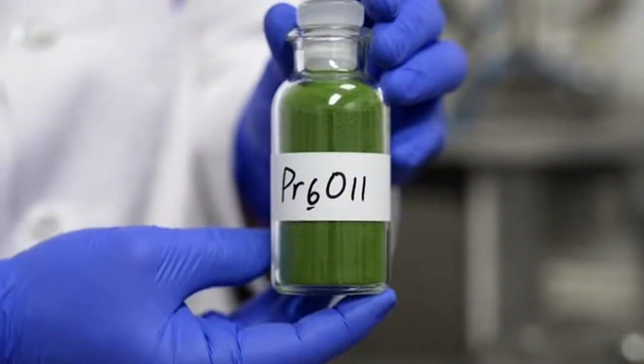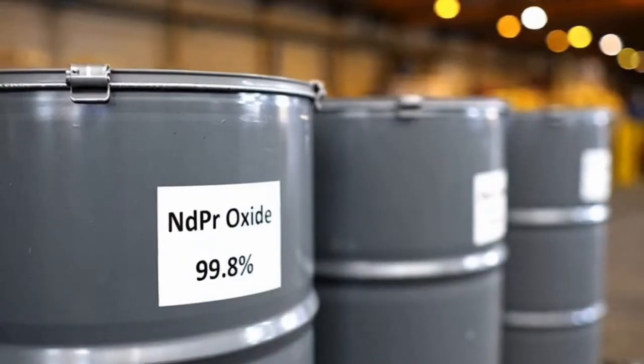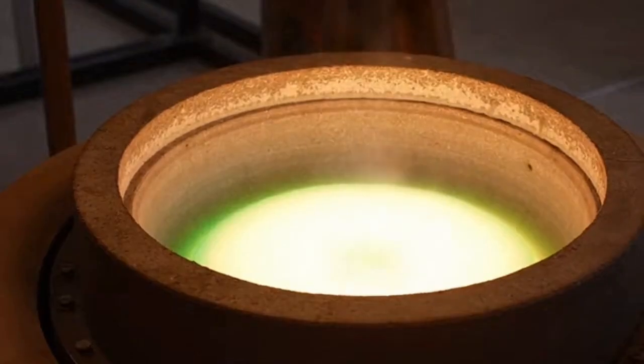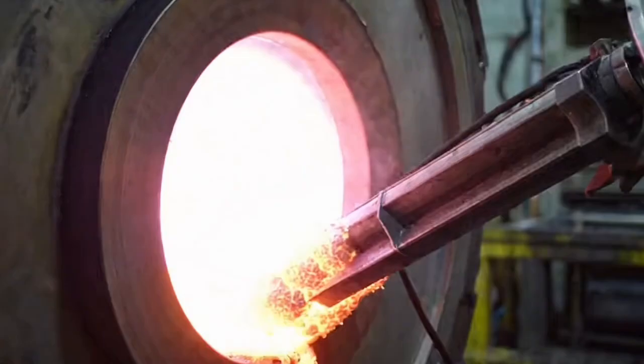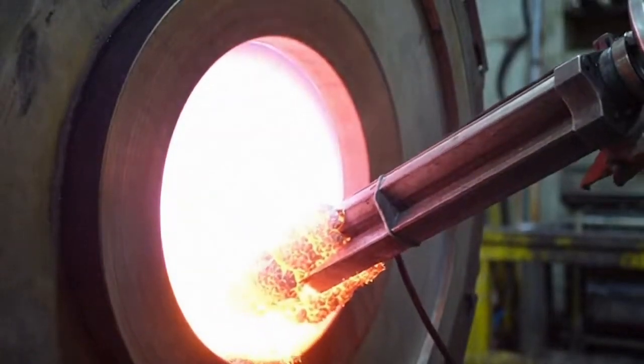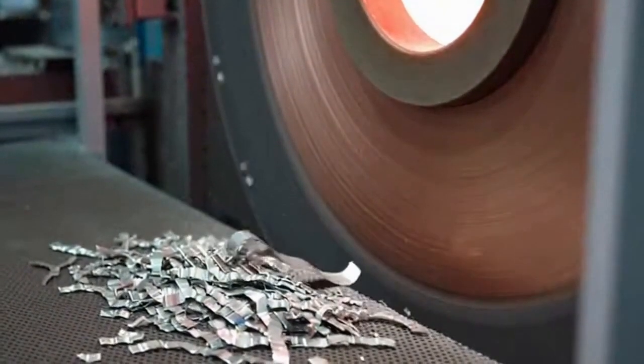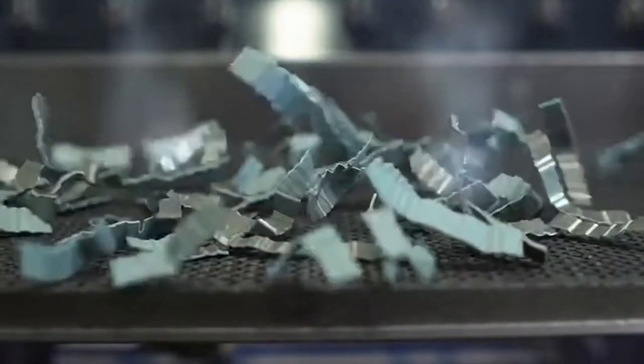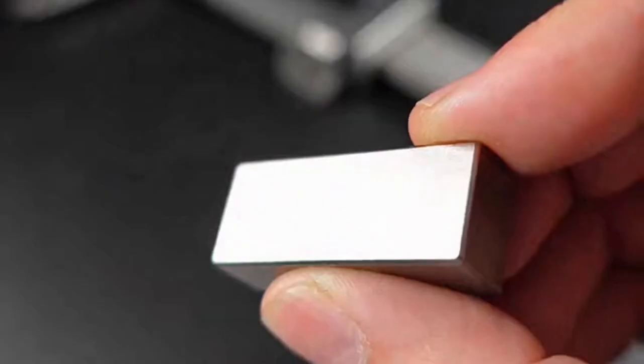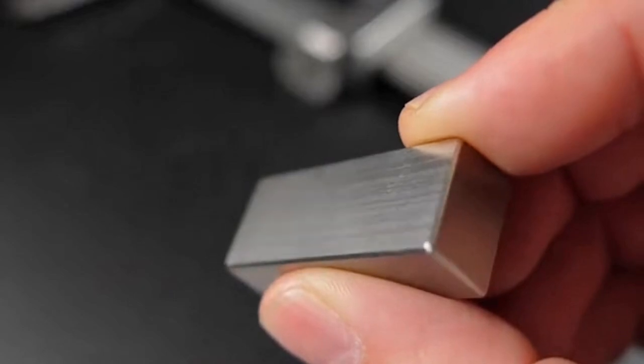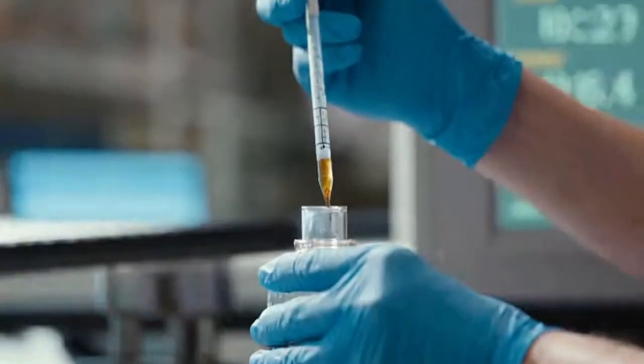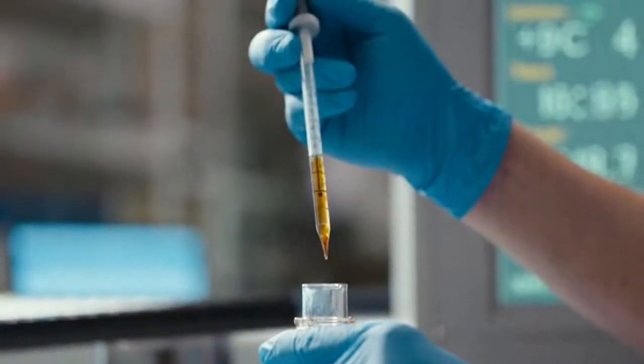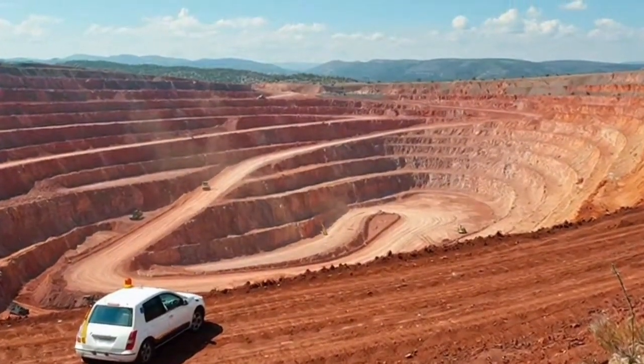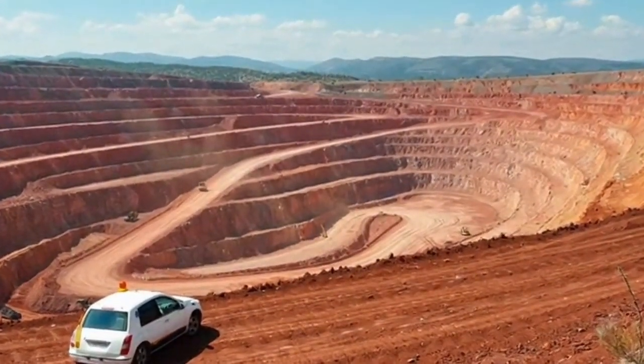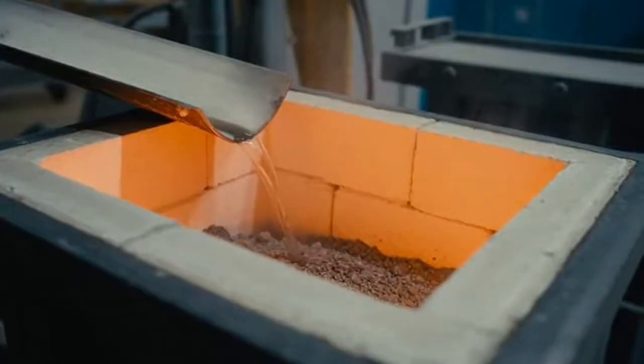The crumb that results is ground, usually by jet mill, into a powder with a size distribution that the press cares about. Under a strong magnetic field, you press the powder so that grains line up their easy axes of magnetization. You sinter to densify, carefully, so the grains do not coarsen into laziness. Then you anneal, because the crystal remembers heat like some people remember childhood. At the end of this, you have an oriented, dense piece that, after machining and plating, is a magnet.